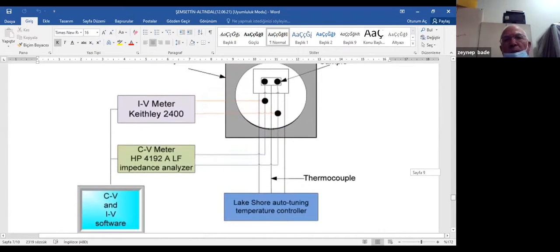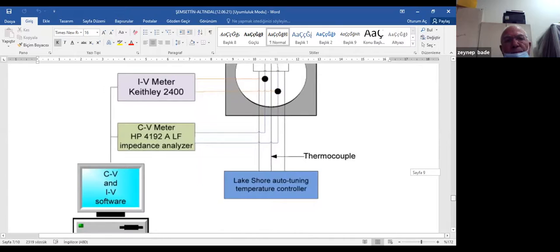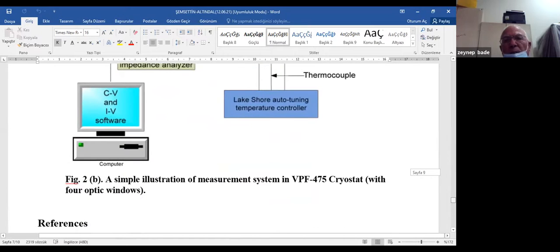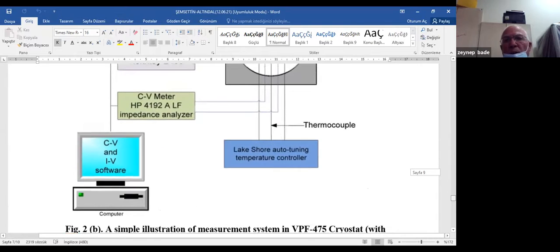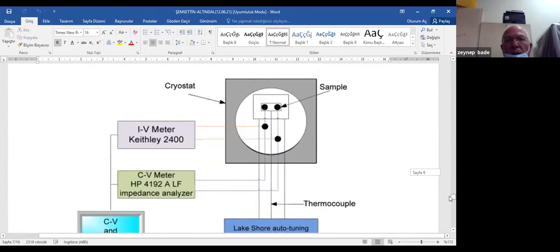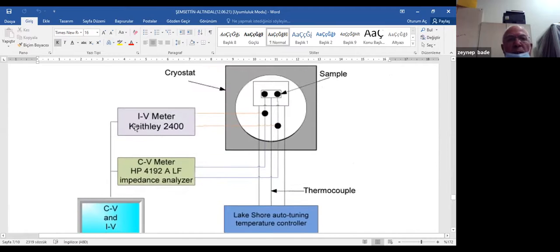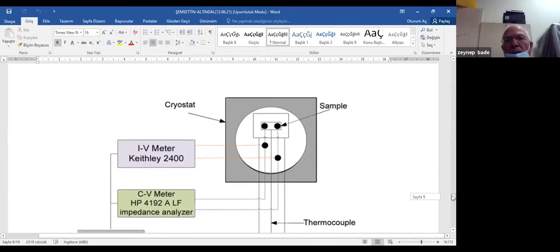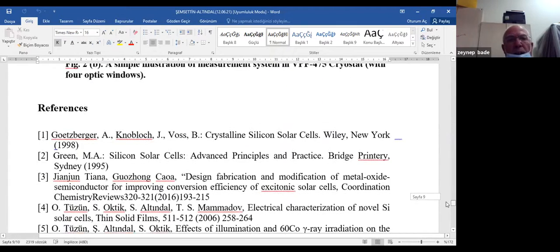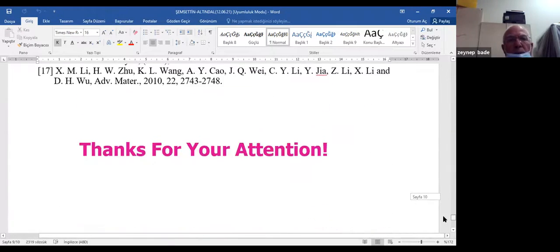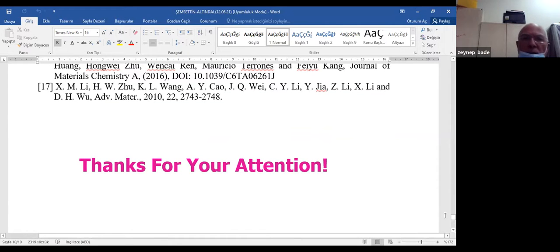Electrical characterization of the Schottky barrier: usually in my laboratory we use a VPF cryostat with four optic windows and use current-voltage measurements and an HP impedance analyzer, both in the cryostat condition and in the dark. So, thanks for your attention.